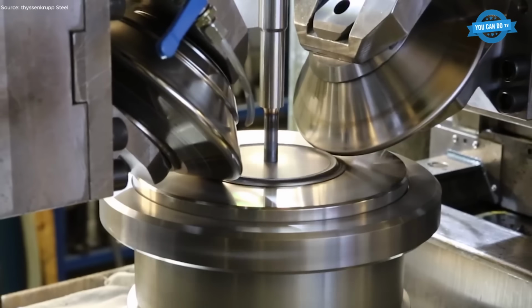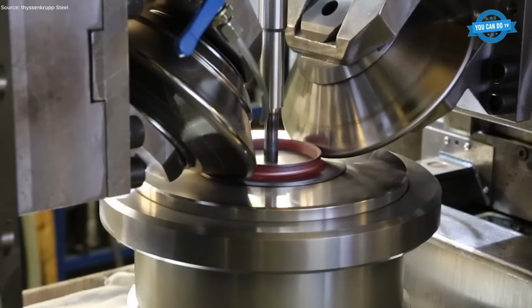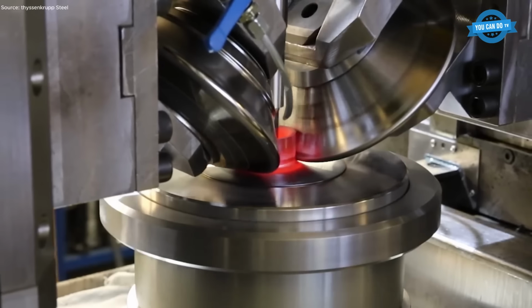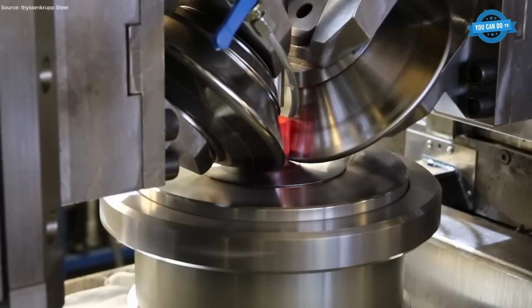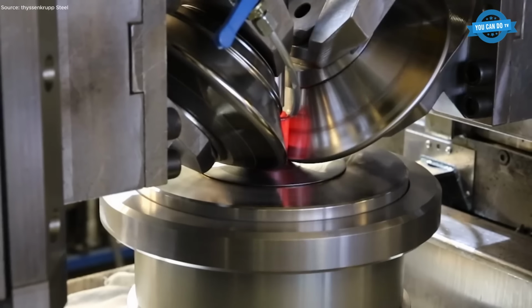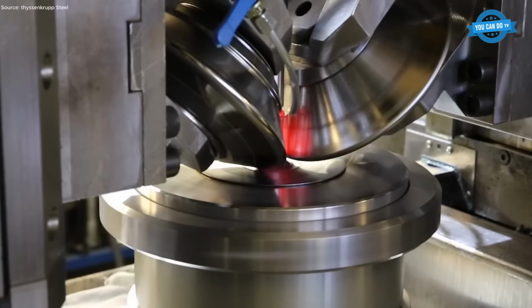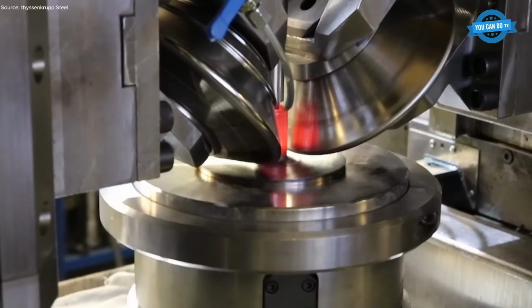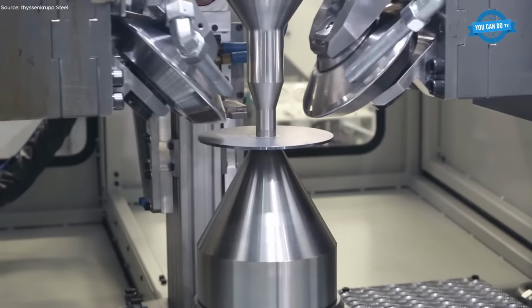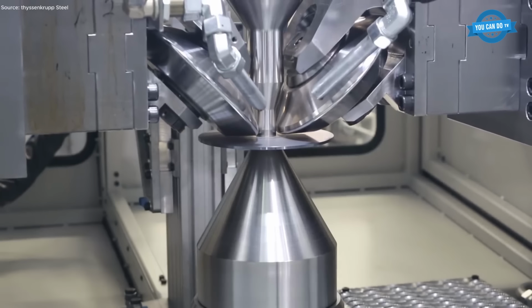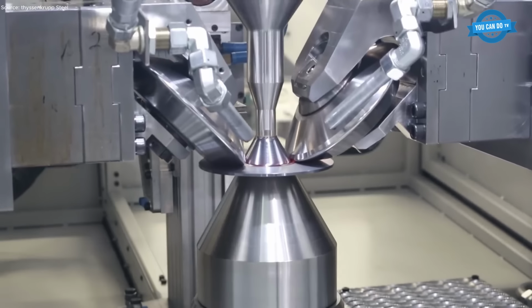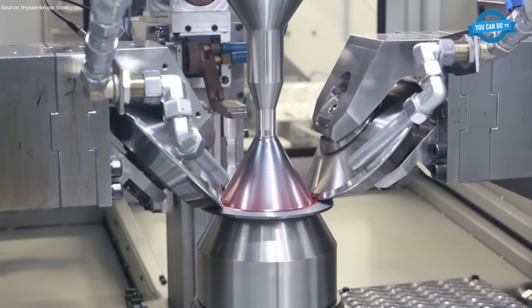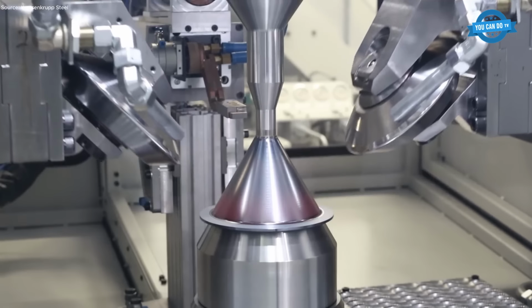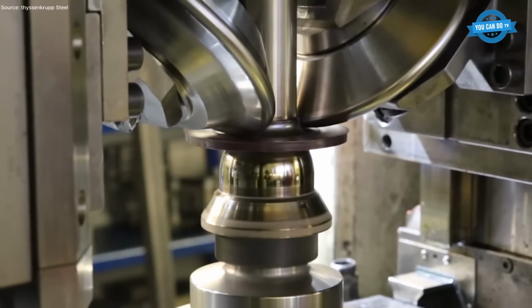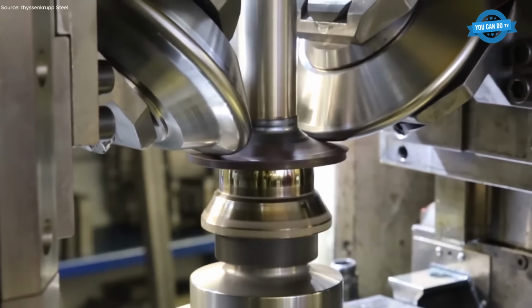At ThyssenKrupp Steel, warm flow forming enables the production of high-precision automotive components that are up to 50% lighter than welded or cast alternatives. The technology combines controlled heating with flow forming to shape rotationally symmetric parts from sheet or tubular preforms. During processing, the workpiece is set in rotation and locally formed by rollers, forcing the material to flow axially along the tool geometry.